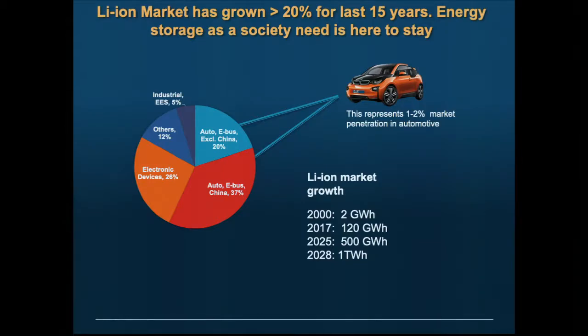If you look at only 25% of lithium-ion went to electronics anymore. This is your smartphone, your laptops. Already more than 50% went to automotive. Now I want to put that in perspective. That's 50% of all lithium-ion, but that represented only about 1.5% of the automotive market, right?